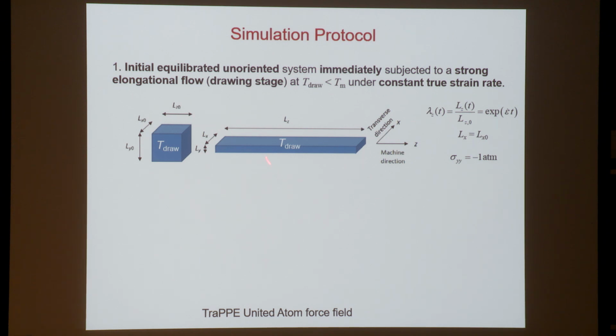sub-Tm temperature, and then we subject it to a deformation with non-equilibrium molecular dynamics that pulls it in the X direction. It keeps the Z direction constant to sort of emulate this film geometry, and it exposes the Y direction, top and bottom, to atmospheric pressure, so the film shrinks in that direction. The deformation is imposed with a specific true strain rate, epsilon dot, and as we mentioned, Lz is equal to Lz0, it's constant, and sigma yy, the stress in the Y direction, is -1 atmosphere.